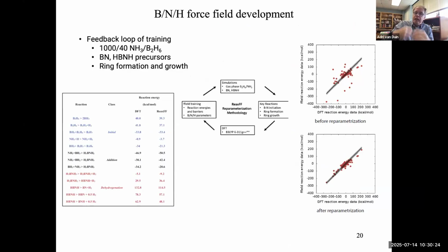We go back to DFT, and you see initially this force field actually is pretty bad. There's really a very bad fit between ReaxFF and DFT. But we add these things to the training set. In a couple of cycles, we get a force field that actually becomes predictive and much more accurate for these systems.